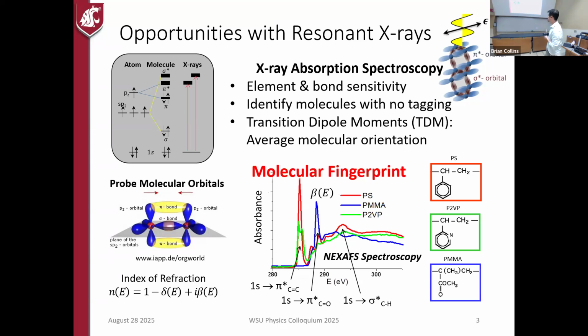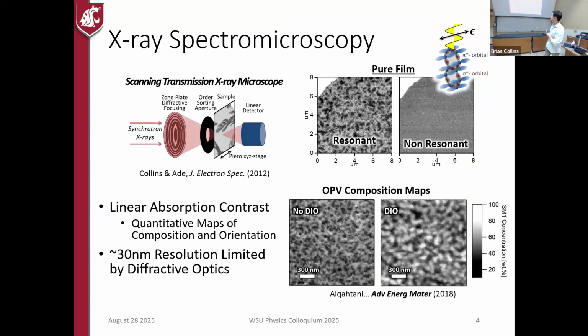So from this absorption measurement, we like to parameterize the interaction of the X-ray with the material, and we like to use the index of refraction. Through absorption, you might know that's the imaginary part of the index of refraction, right? And if you've taken a math methods course, the Kramers-Kronig transformation gives you the real part. So through this one measurement, we can measure the entire complex index of refraction across this absorption edge and characterize the molecular interactions that way. So what does this allow?